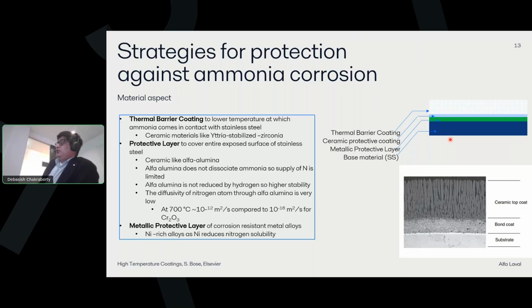A protective layer could be alpha alumina, because alpha alumina is pretty much non-penetrable to nitrogen. As you can see at 700, the diffusivity is on the order of 10 to the power -6 compared to 10 to the power -12 for... Okay, this is reversed actually: 10 to the minus 12 for alumina compared to 10 to the minus 16 for chromia. Then there is a metallic protective layer that could be applied, like a nickel-rich layer. As we have already seen before, nickel reduces the solubility of nitrogen in the metal. And when you do that, it could look something like this.